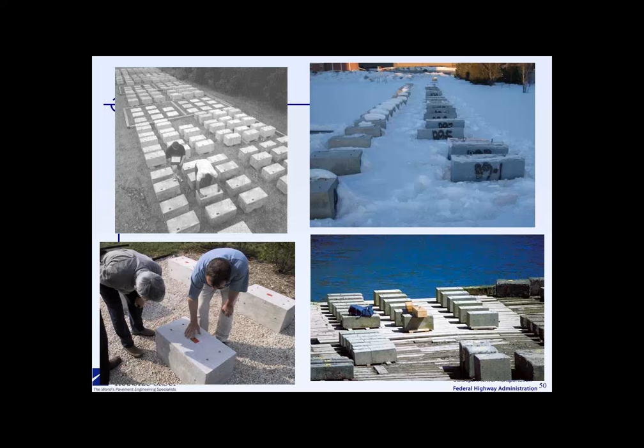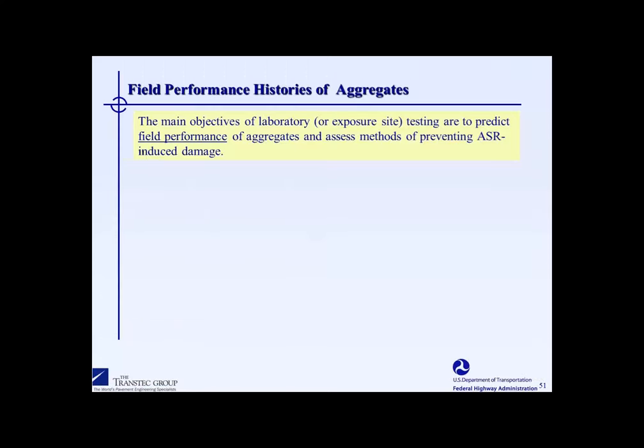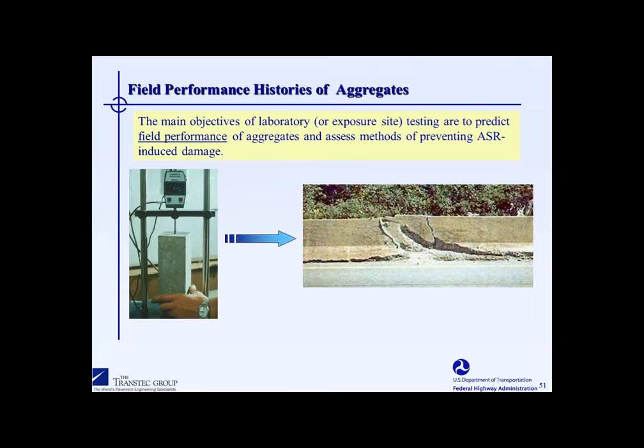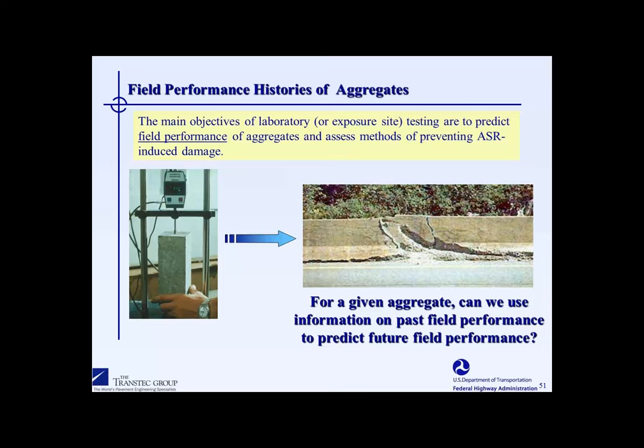And on the bottom left is the Austin, Texas site. These sites are really proving to be invaluable in terms of underpinning our test methods. But one thing we have to be clear about is that sometimes exposure sites might take 10 or 15 years to bear fruit in terms of expansion results. And it means that with time, we will be changing our recommendations for lab tests as we learn more about field performance.